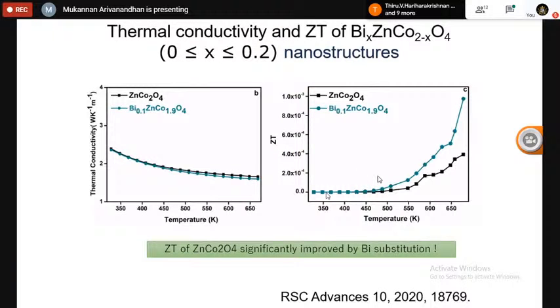And the best sample has been chosen to measure the thermal conductivity, and the thermal conductivity of the bismuth substituted sample is quite low, especially at high temperature, compared to the pure sample. And from the measured thermal conductivity and power factor, the ZT has been calculated.